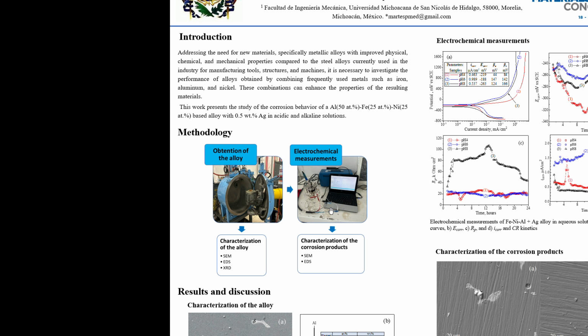From the potentiodynamic polarization curves, anodic and cathodic slopes, which are beta A and beta C, were obtained using the intercept method. On the other hand, the polarization resistance measurements were carried out in the range of plus and minus 15 millivolts versus the open circuit potential, and a scan rate of 1 millivolt per second every 15 minutes for 24 hours. From the linear polarization resistance results, the corrosion potential, polarization resistance, corrosion current density, and corrosion rate kinetics were estimated following the standard method.